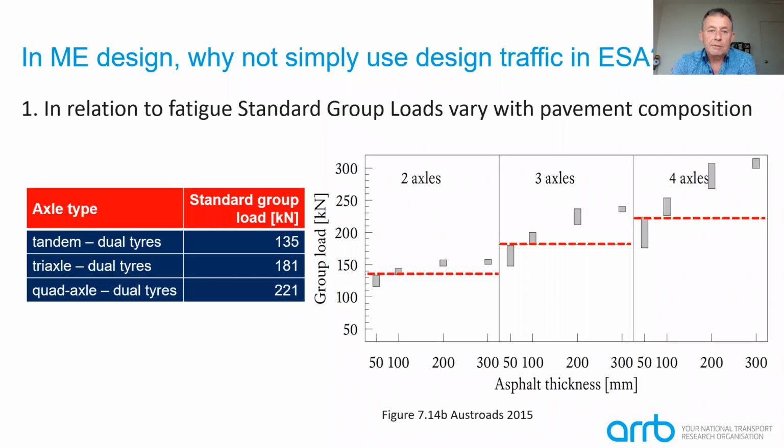So the first question might be, why don't we use that simple method of ESAs in the mechanistic empirical design method? It's a much simpler system to use. As part of that research that I mentioned earlier, we examined that issue and basically found that those standard group loads, although they're applicable to the rutting of granular pavements, they're not applicable to the fatigue of asphalt or cement materials. And you can see in this graph here how the standard group load would actually need